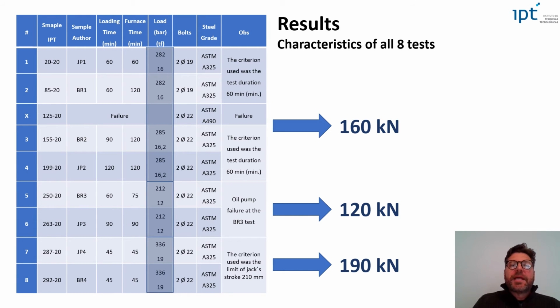As I said, another 6 tests, or 3 more pairs of beams with different steels, were carried out, but with slight changes in the mechanical loadings. What we saw is that for the other tests, the same curve shape, but with different magnitudes. Here you can see the 1, 2, 3, 4 pairs of samples, being a fire-resistant steel and a conventional steel for each pair.